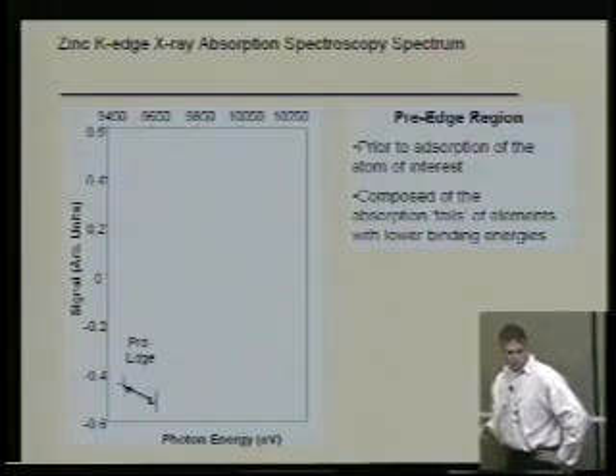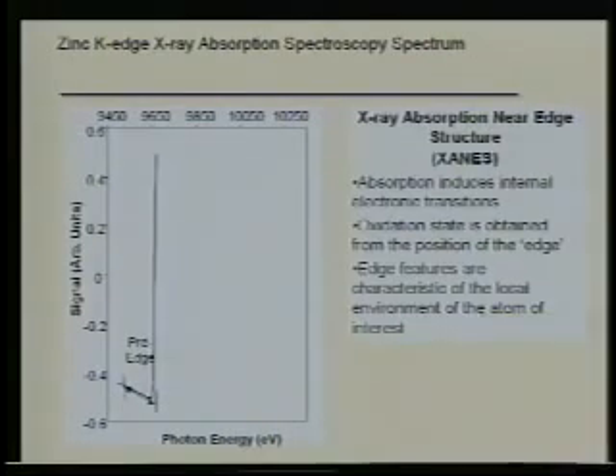Then as we come to the absorption edge, this is called the XANES, or the near edge structure. And this actually maps out the densities of states, of the empty states in the conduction band for a semiconductor, or above the Fermi level for a metal, or for molecules, it's basically probing the LUMO, the lowest unoccupied molecular orbitals. So this provides information on oxidation state, and actually can give you chemical information because of the bonding.